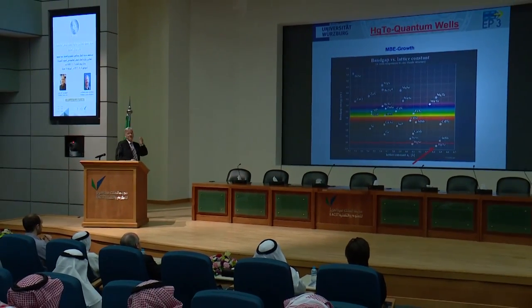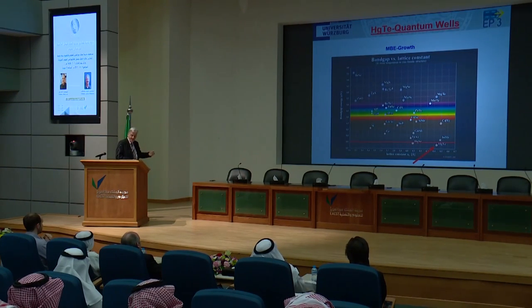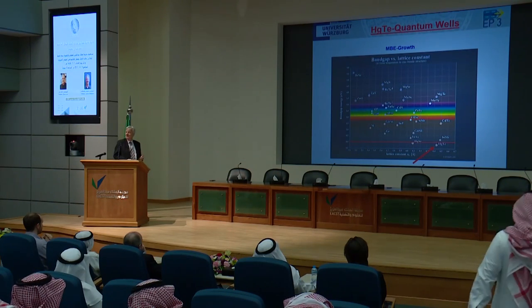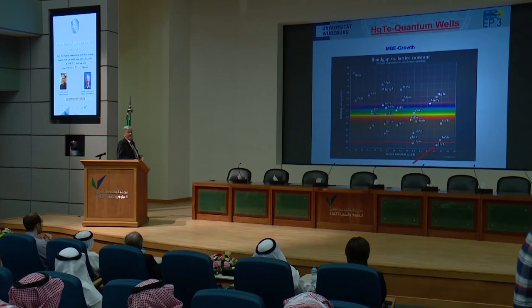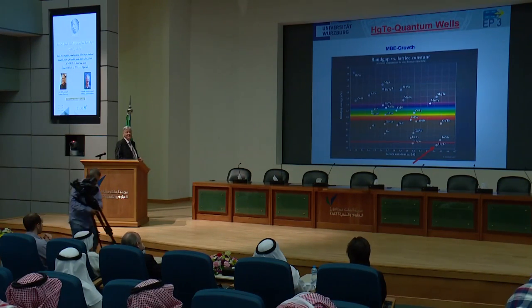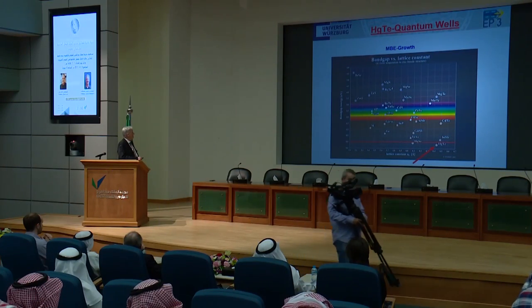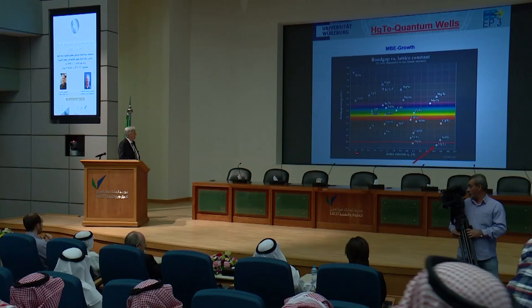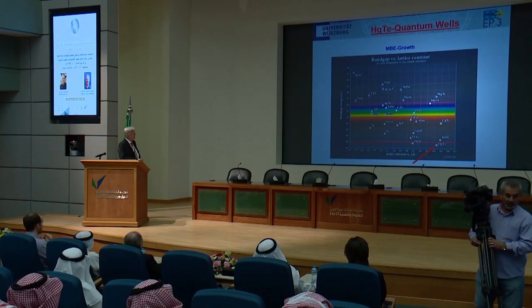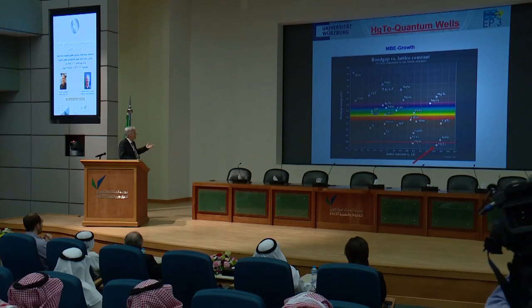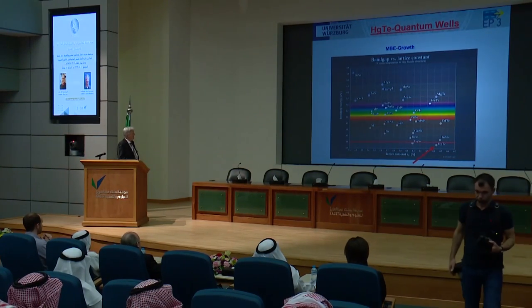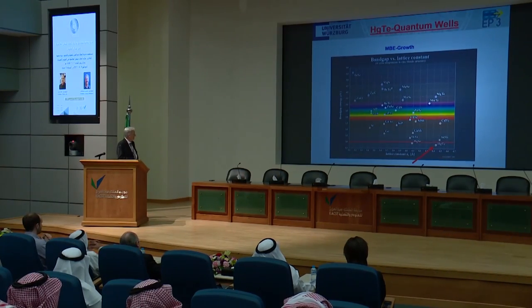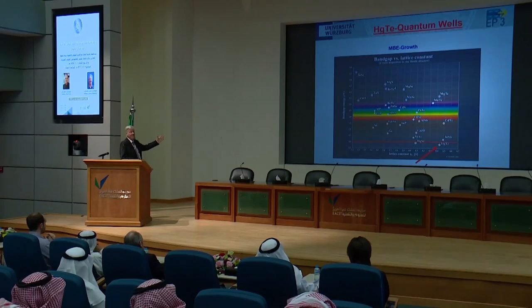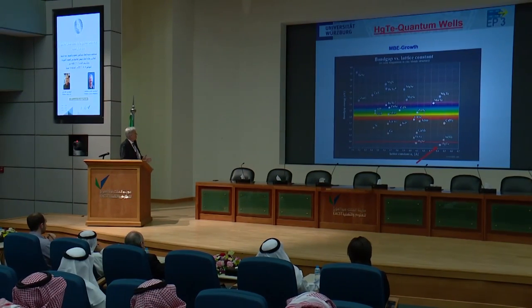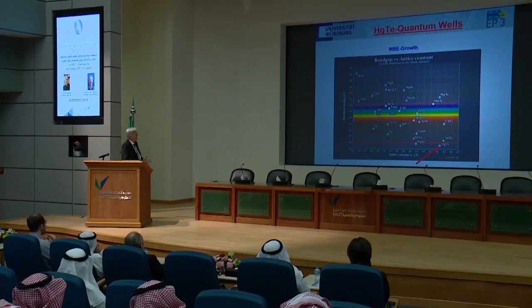So this is a plot that I was given when I came to Würzburg in 1999. Würzburg has many MBEs for growing semiconductor heterostructures. And in order to help me to keep track of what we could grow, they gave me this graph here. What you see is basically all kinds of zinc blende semiconductors. This is their lattice constant and this is the band gap. They all have the same crystal structure, but of course because some atoms are bigger than other atoms, they all have a different lattice constant. And you see they group up in columns here, and these columns are the materials where you have the same lattice constant. So these you can easily grow on top of each other. So this is what I needed to know.